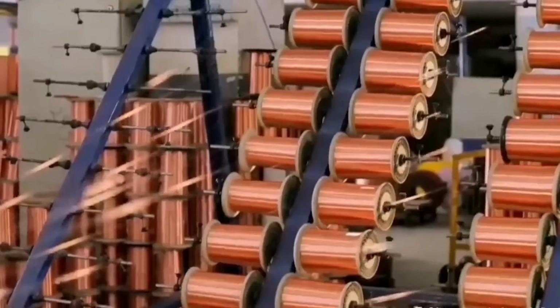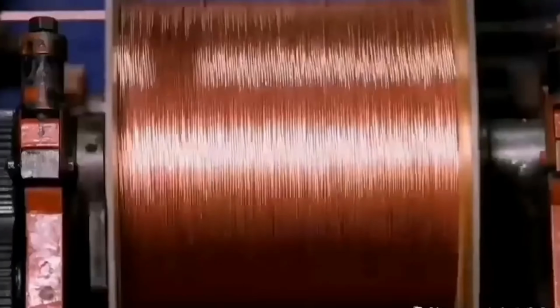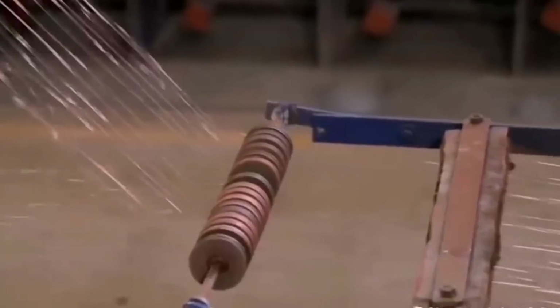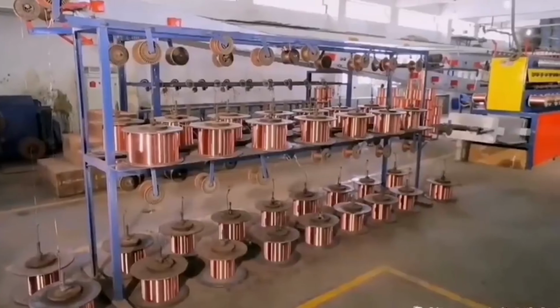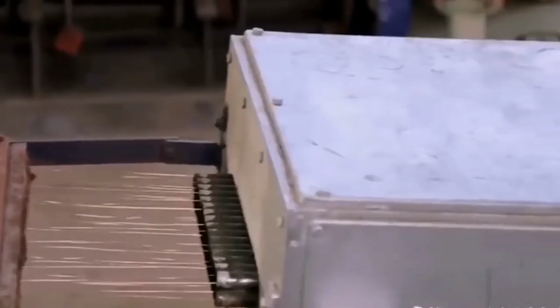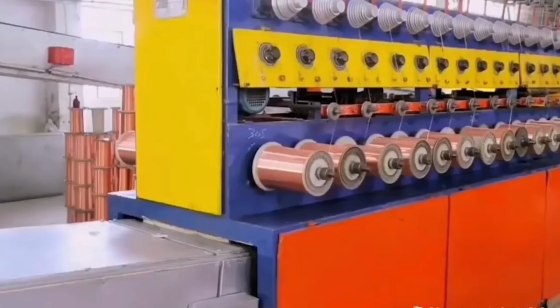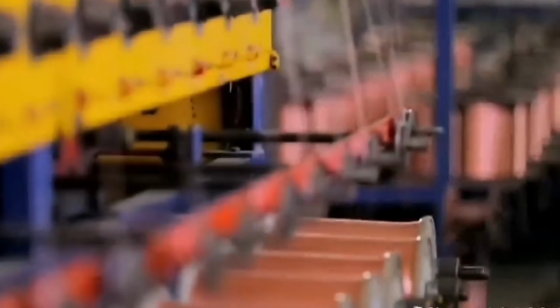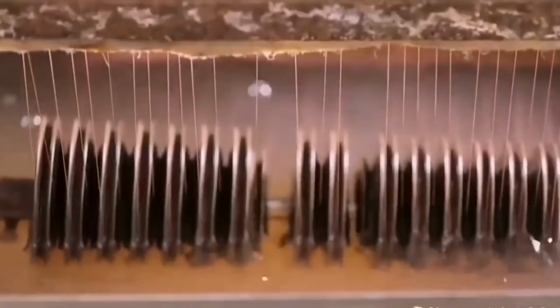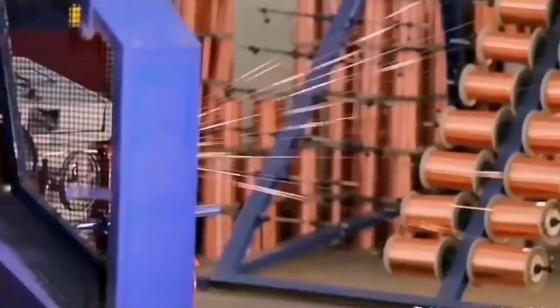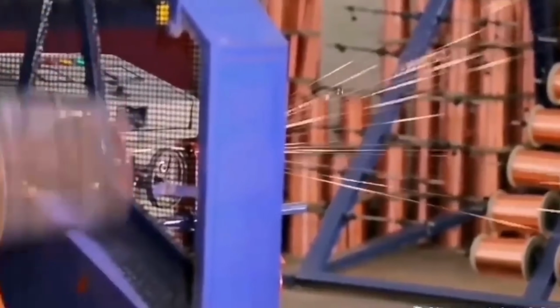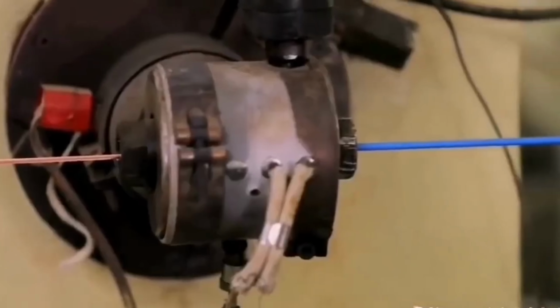Hard wire is brittle and unsuitable for electrical use, so the wire undergoes annealing, a heat treatment process that softens the copper while preserving its shape. Inline annealers use electrical current passed directly through the moving wire. As the current flows, the wire heats rapidly to several hundred degrees Celsius. Water sprays cool it immediately afterward, freezing the copper's crystal structure in a softened state. This makes the wire flexible, bendable, and ready for spooling or further processing.